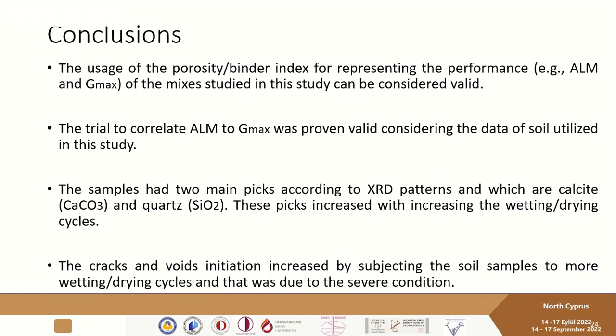Also, the usage of the porosity binder index for representing the performance of the mixes studied in this study was valid, and also the trial to correlate between loss of mass and maximum shear modulus was proven to be valid. And also, according to the XRD, the main peaks in the mixes were quartz and calcite, and these peaks were getting increased by subjecting samples to more wetting drying cycles, and also the cracks and voids initiation increased by subjecting the soil samples to more wetting drying cycles, and that was of course due to the severe conditions.